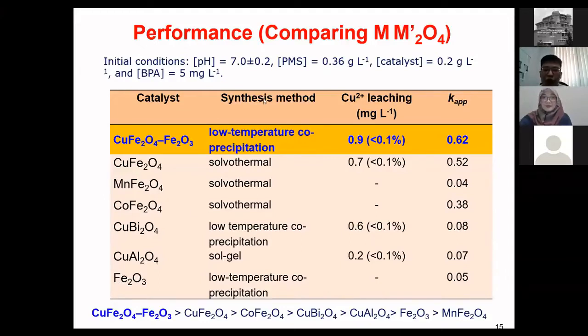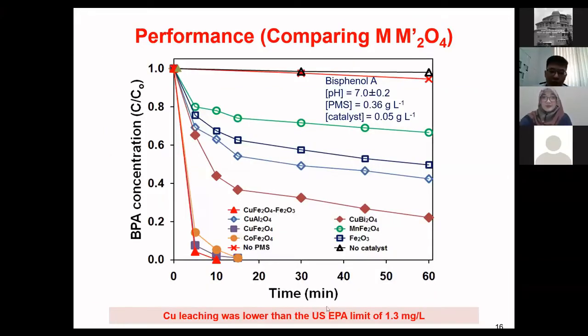So of course we are not satisfied, because there is still leaching, copper leaching. You can see here up to 0.9 ppm of copper still leaches out from the solution. Although it's within the US EPA limit, the US EPA limit of copper is about 1.3 milligram per liter, but then leaching is still leaching. We still have to solve this problem, right? So you look at the performance, it looks very good compared to other catalysts.